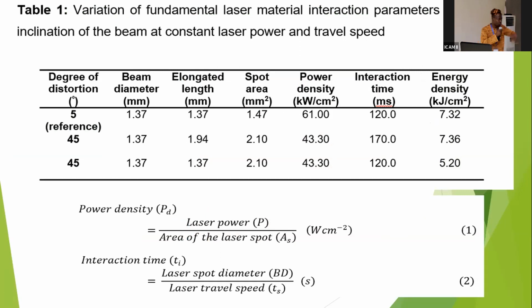Even if you keep the same travel speed and the same laser power, because the area has changed, the power density, which is actually responsible for the melting, is not going to be exactly the same. So if you increase the area, you decrease the power density, as you can see there. If you make the area smaller, you increase the power density, and this has a great influence on the energy input to the system.